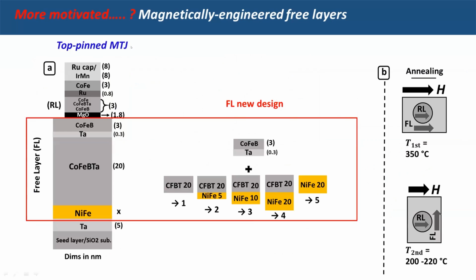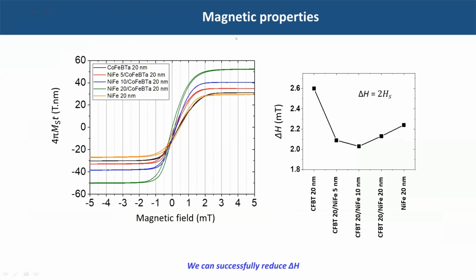And this is our top-pinned MTJ. This is how we suggested the new free layer design. For example, this is CFBT, just 20 nanometer. We coupled it with 5 nanometer nickel iron, and then 10, 20. And we also compared with 20 nanometer nickel iron. And then we again did the two-step magnetic annealing technique. And I'm sharing with you here the result of